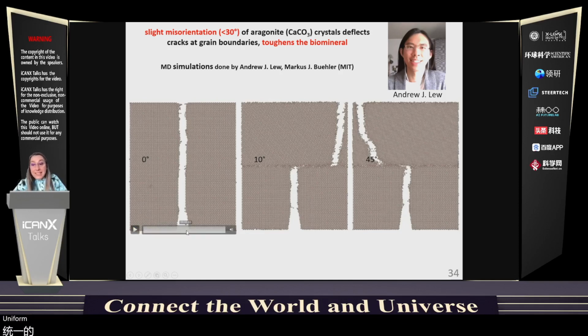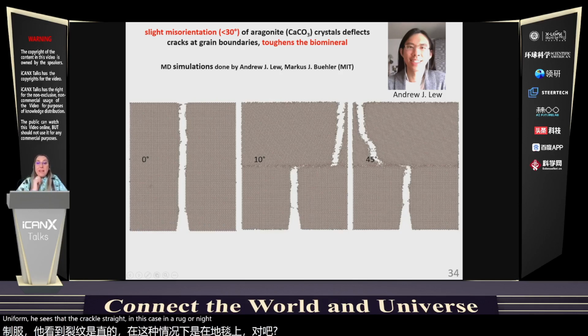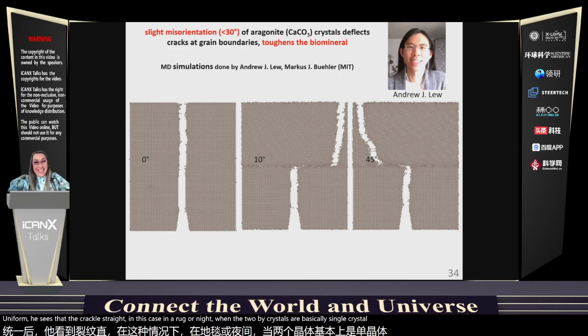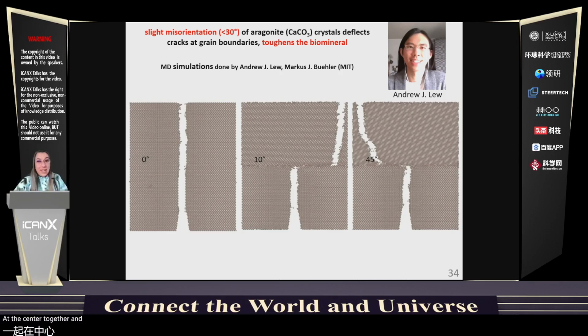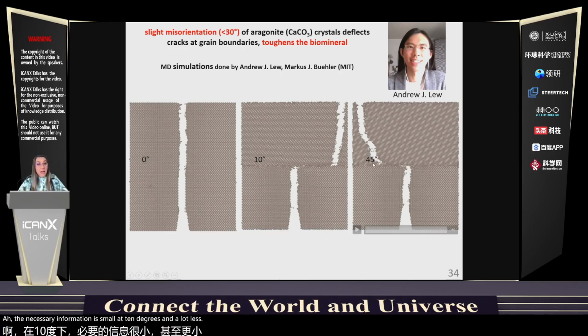Beautiful. He sees that the crack goes straight, in this case in aragonite, when the two bicrystals are basically a single crystal. They are sintered together and they have precisely the same orientation. The crack is very much deflected at the interface when the misorientation is small, at 10 degrees, and a lot less deflected at 45 degrees, a greater misorientation angle.